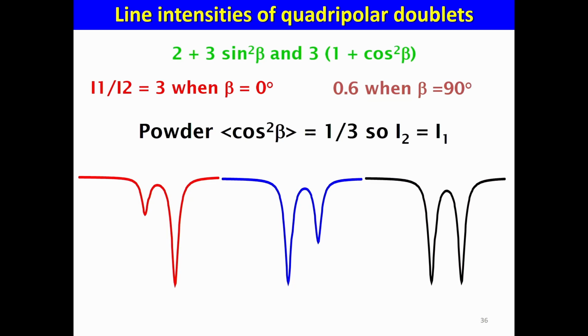What is usually called, for X-ray diffraction, preferential orientation. And you can see a change on some peaks. But in the case of Mossbauer, it will be the same. So one solution is to rotate the sample with respect to the gamma beam. If you see some changes in the intensities of lines, that means it is due to some preferential orientation. If not, it can be due to other things. Or sometimes it is only because you have 2 components which are superimposed with very close hyperfine parameter values.